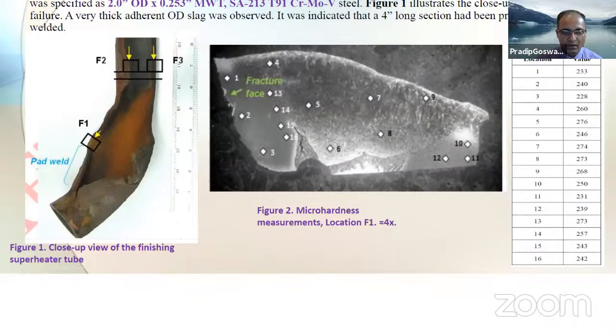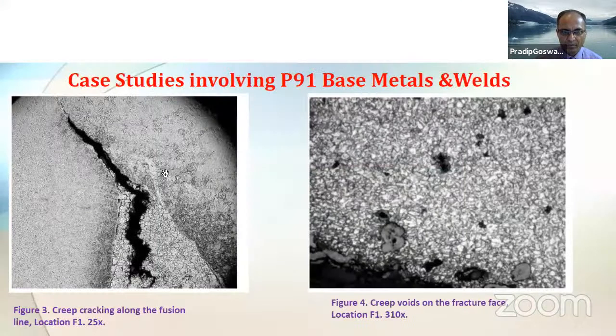It is just like when you have a minor leak and you try to glue that leak with a pad weld. That works typically for carbon steel and low alloy steels, but it is not the way it should have been done for grade 91 steel. But anyway, this pad welding was done, and later this pad welding failed, and this tube ruptured, and that caused a forced outage for that utility.